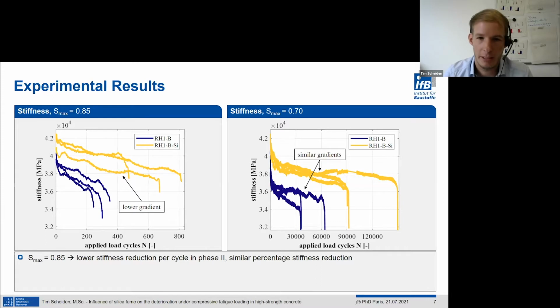The next damage indicator is the stiffness, which is defined as the secant modulus in the decreasing branch of the hysteresis loop. At the higher stress level on the left side, based on the gradients, it becomes clear that the addition of silica fume leads to a lower stiffness reduction per load cycle in the second phase. But due to the higher number of cycles to failure, the overall percentage stiffness reduction is similar to the concrete without silica fume.